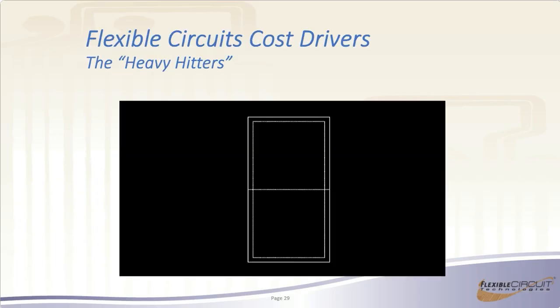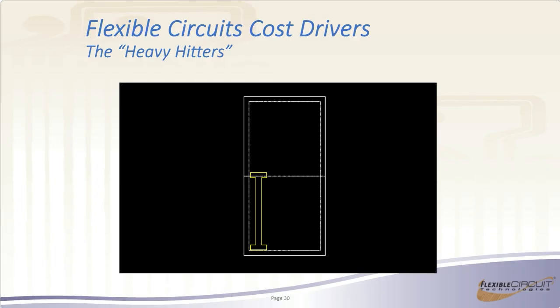As an example, I first want to state that almost all flex circuits, while very high volume, million piece or more orders are done roll to roll, the vast majority of flex circuits are done in panels. So if you were looking at a panel here, let's say just for argument, this is a 12 by 24 inch panel with a little bit of border on the outside for tooling holes. And you design your flex circuit and you need a certain length, you add a little bit extra service loop in there. And so when you send that to your manufacturer, he puts it on the panel and it turns out that it's just slightly over the halfway mark.